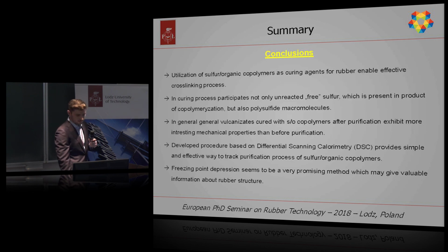So to sum up, utilization of sulfur organic copolymers as curing agents for rubber enables an effective cross-linking process. And in the curing process participates not only unreacted sulfur, which is present in the product of copolymerization, but also polysulfide macromolecules, and it was confirmed by the cross-linking after purification. In general, vulcanizates cured with sulfur organic copolymers after purification exhibit more interesting mechanical properties than before purification. And the developed procedure based on DSC provides a simple and effective way to track the purification process of sulfur organic copolymers.